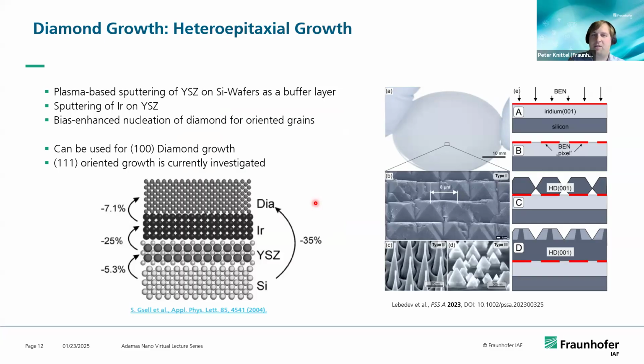So they started working on this technique using a silicon wafer that has a buffer layer consisting of yttrium stabilized zirconia and on top an iridium layer. With that, the lattice mismatch can be adapted, and you can use so-called bias enhanced nucleation to form oriented grains on a silicon wafer. With that, you're in principle not limited in size anymore, even though the nucleation on a large wafer has some challenges. But this is the approach that is used.